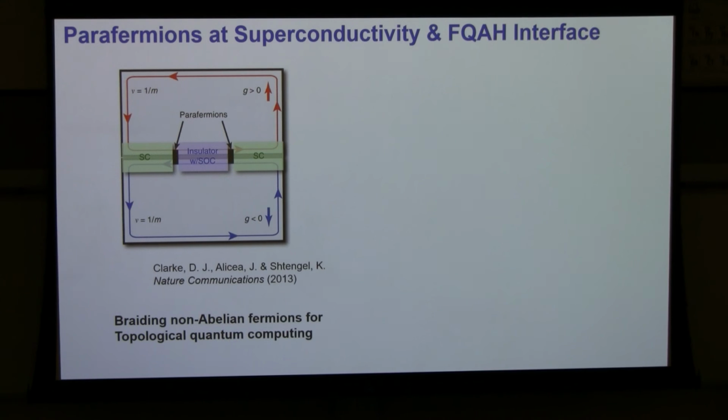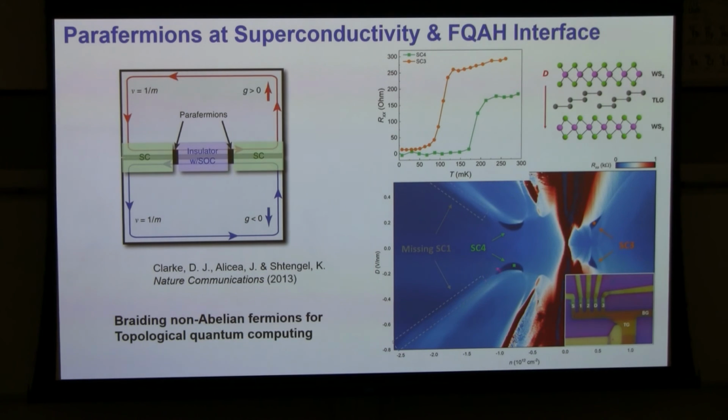And experimentally, we know there is superconductor in such a rhombohedral graphene. This is not exactly 5-layer. This is ABC trilayer graphene. There's some spin-orbit coupling, but there are superconducting states that we can observe, and maybe we can look deeper into it and make some kind of complicated structure in the same flake of graphene without borrowing another material. Because the problem when you bridge 2 different materials is, do they get along with each other or not? This is a nice platform. You have very different physics that can be gate-tuned in the same flake.